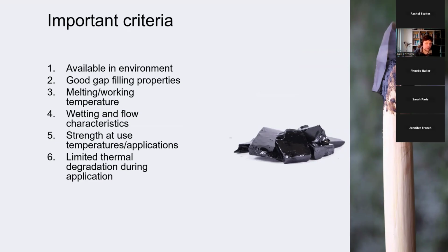So unlike with fine furniture making, with stone tools, there's often a very big gap between the stone tool and the wooden handle. And the adhesive needs to be able to fill up this space. For this reason, hot melt adhesives, so something that you melt to apply, are usually used for gap filling, since they don't shrink very much when they dry. If you have an adhesive that dries by evaporation, it's going to shrink up a lot as it dries, and if you have a big gap, it's going to break away and leave a void in that gap, and it won't be very strong. So another criteria is the wetting and the flow characteristics.